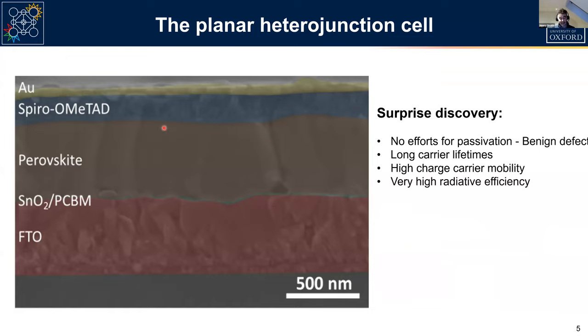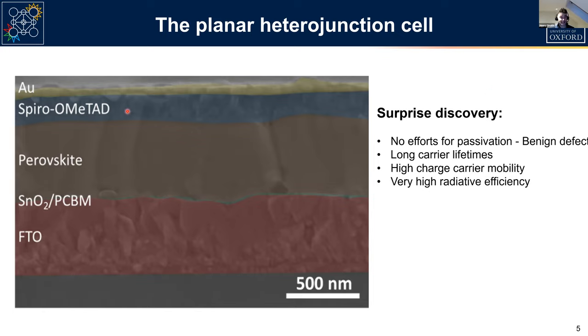This was surprising at the time because we thought perovskite materials were good at absorbing light, but we didn't know they could really transport free carriers — we thought they might be excitonic materials. But it turned out pretty quickly that wasn't the case. We could construct simple planar heterojunction devices with a solid slab of polycrystalline perovskite sandwiched between n- and p-type contacts — the so-called NIP cell, with a tin oxide n-layer, a perovskite absorber, and spiro-OMeTAD as the p-type layer. Interestingly, this hole conductor, first reported in 1998 by Udo Bach and Michael Grätzel for solid-state dye cells, is still present in some of the most efficient devices today.